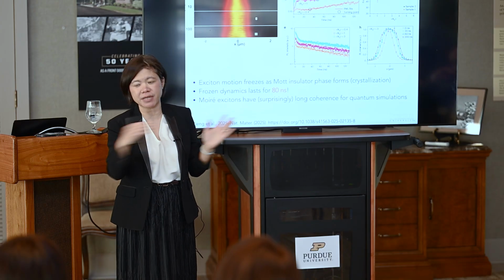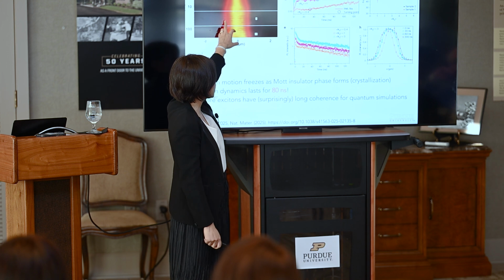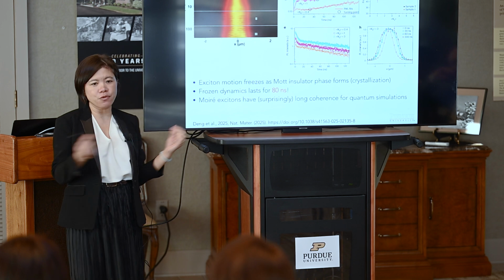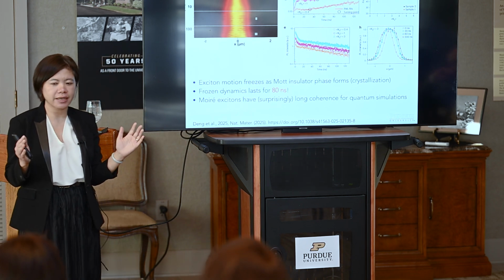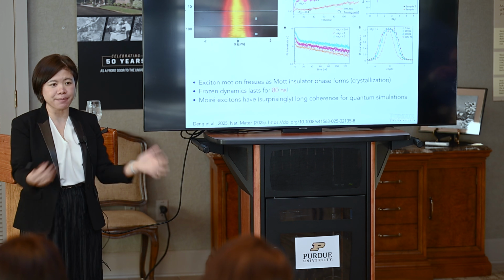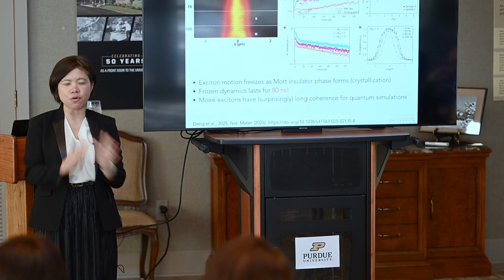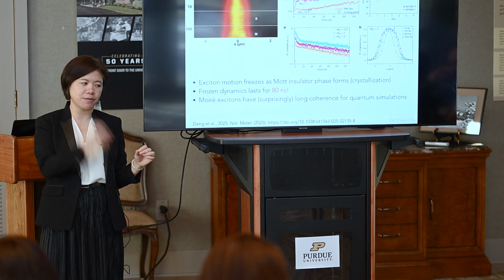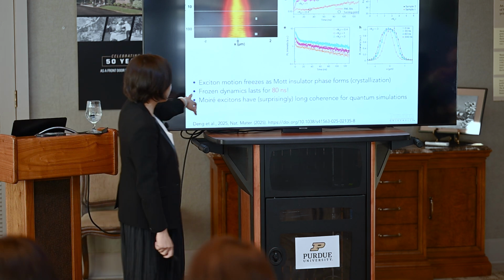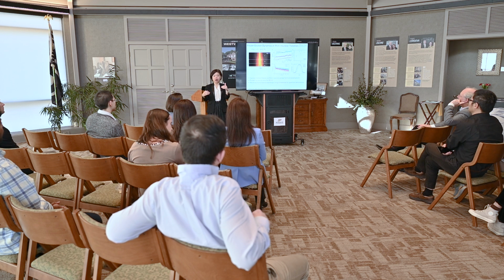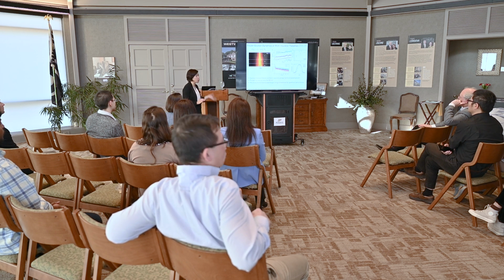And this graph you can interpret as the slope of it being the speed of the exciton. Once it forms this square top, the slope becomes close to 0. So the exciton cannot move at all. So basically we keep adding excitons onto the Chinese checkerboard, and at some point, all the motion totally stops. And that comes from the interaction between these quantum particles. And why it freezes, it has to be that the excitons are still coherent with each other. The reason they can freeze is because the phases of the excitons are still locked. If they're not locked anymore, then they will no longer form this Chinese checkerboard pattern.